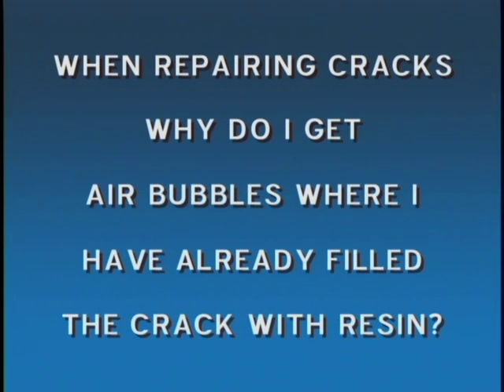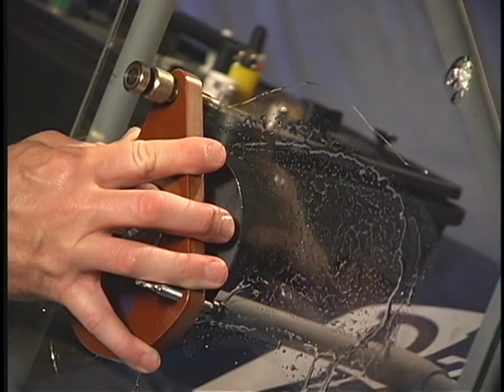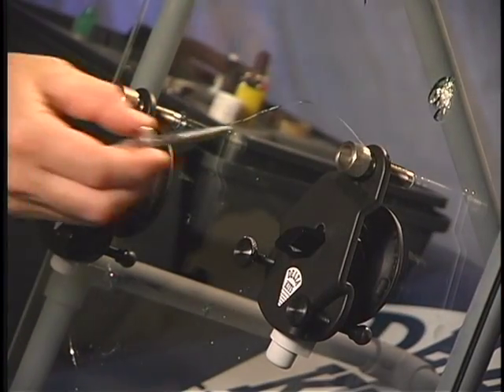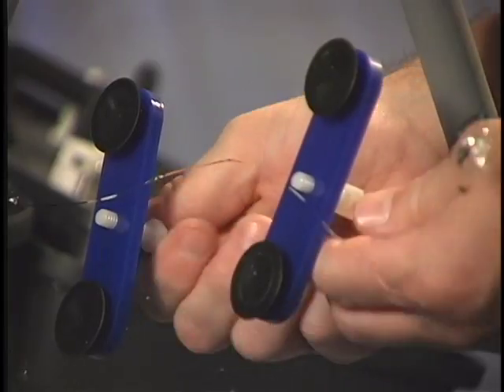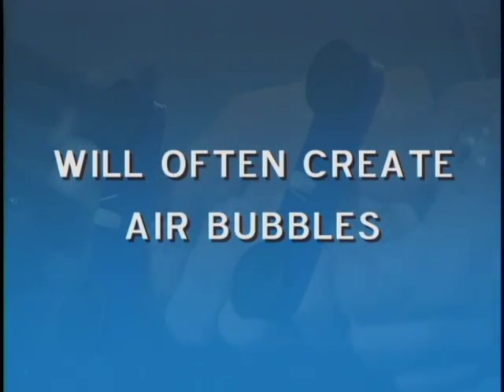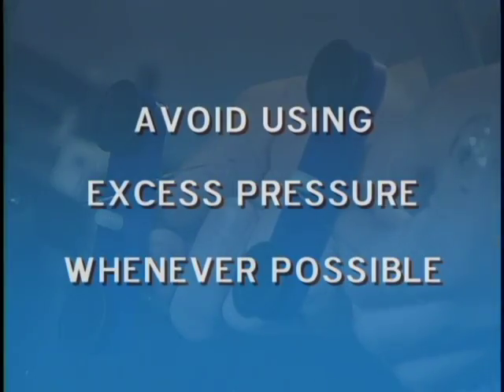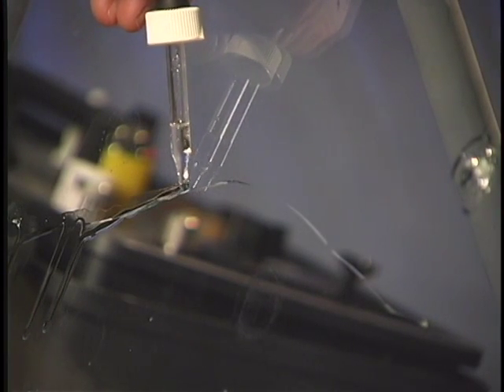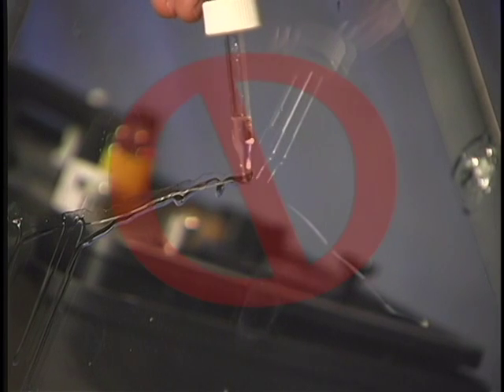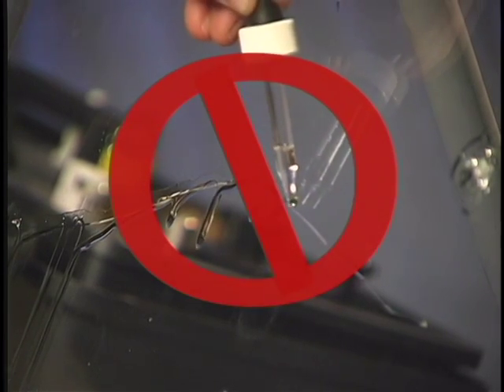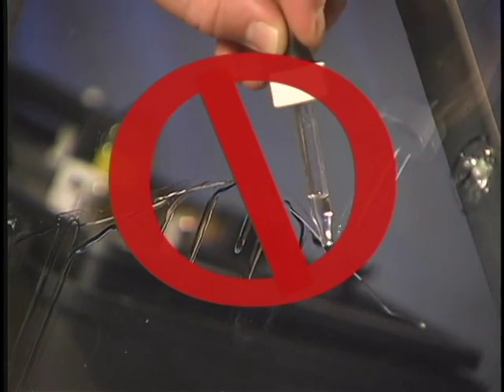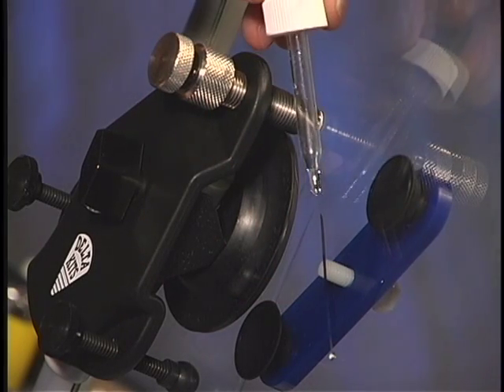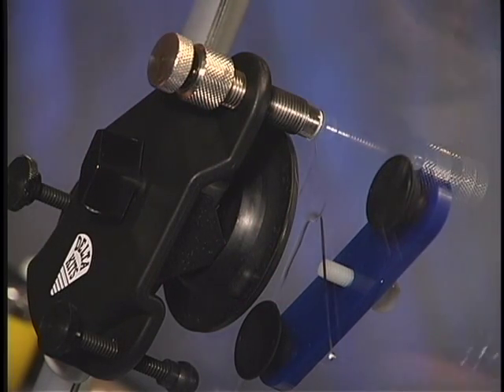When repairing cracks, why do I get air bubbles where I have already filled the crack with resin? Techniques such as sliding a bridge, using an injector at each end, or using a crack spreader will often create air bubbles. It's best to avoid using excess pressure whenever possible. If you simply run resin along the crack, it will seep in at different places depending on the width of the crack. Always fill the crack from the impact point until it will travel no farther into the crack.